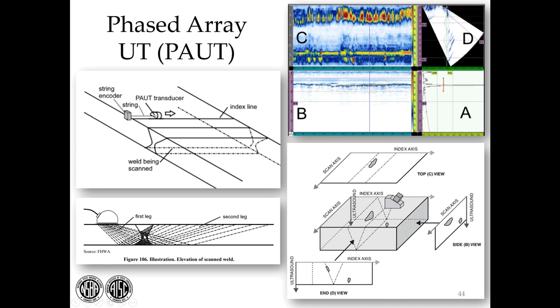So in this particular weld, the fabricator might put a transducer here, scan, and then move the probe here and scan the rest of the weld. Under the code with phased array, you must establish a scanning plan that says, here's where I'm going to put my transducers to make sure that I've got coverage in the weld. So you see here in this view, the phased array probe is put on an index line. We have the weld here. The fabricator would decide where he wants to put the probe and then draw a line, say, all right, that's my index line. And then I'll run my transducer along the line.